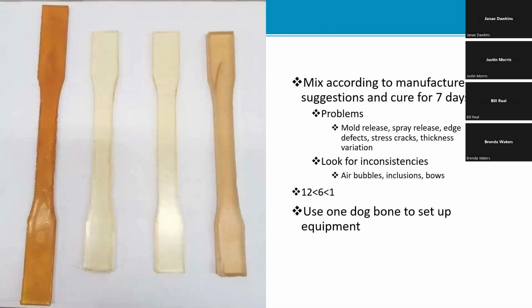So you want to make sure that some of the problems you're going to run into when you're using the molds for the dog bones, you have to use a mold release. If you don't use the mold release, you're going to have problems with pulling a sample out of the molds. So you want to use a spray release.